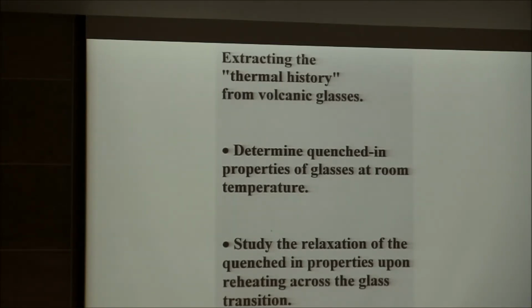Okay? So this technique, although absolutely trivial to explain to you, turns out to be impractical, and this is the life of an experimentalist, you always have to know what is practical, what is a significant investment there. So the other way we can do it is this one. This one is much more complicated to explain to your mother, but the basic idea is you take the glass, you heat it back up across the glass transition, so you literally drive it into the liquid state again in a calorimeter, and you watch how it relaxes as it goes back to the liquid state. And how it relaxes, exactly measured, gives you the hysteresis, which you can use to interpret the initial cooling rate of the glass. Okay.